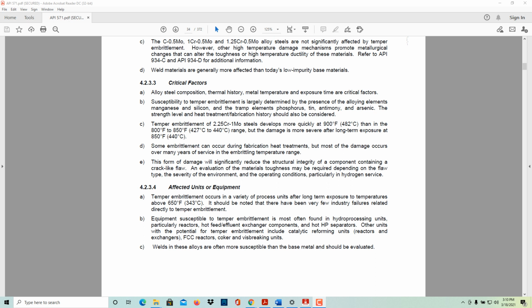Temper embrittlement of 2.25 chrome 1 moly steels develops more quickly at 900F than in the 800 to 850F range, but the damage is more severe after long-term exposure at 850F. Some embrittlement can occur during fabrication heat treatments, but most of the damage occurs over many years of service in the embrittlement temperature range. This form of damage will significantly reduce the structural integrity of a component containing a crack-like flaw. An evaluation of the material's toughness may be required depending on the flaw type, the severity of the environment, and the operating conditions, particularly in hydrogen service.